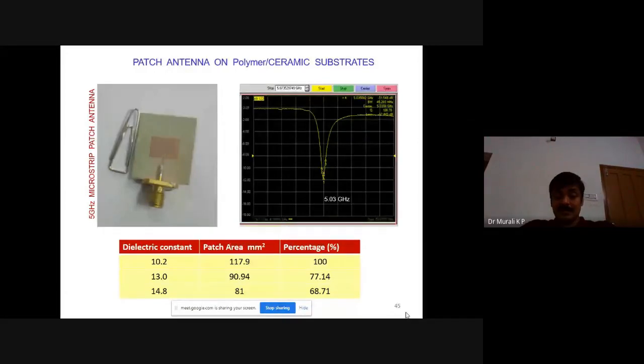So in this case, as I was telling, we were able to enhance the dielectric constant from 10.2 to 14.8 as shown in the chart. What is the advantage of increasing the dielectric constant? When you make an antenna, we can reduce the size, we can miniaturize. Almost 31 to 32% miniaturization is possible since the dielectric constant has increased.